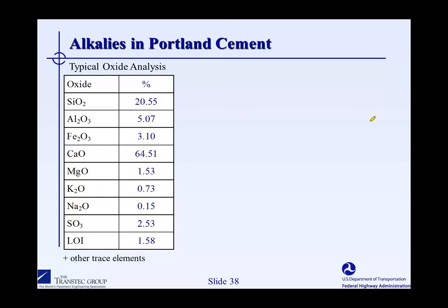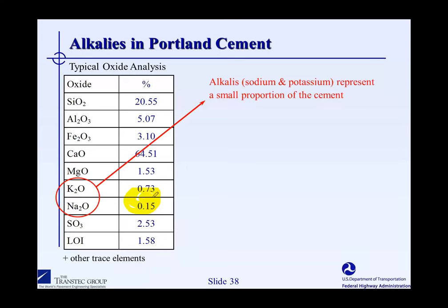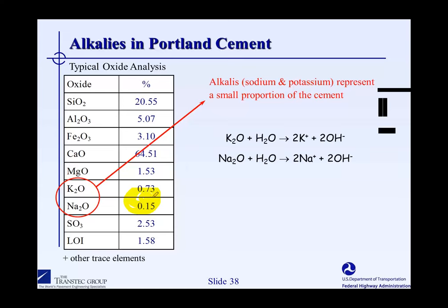If we look at a typical oxide analysis, which you can see here on the left, we know Portland cement's a calcareous material, it's predominantly calcium oxide. Most cement plants are sited near a source of limestone. That's the main ingredient. And then the second highest ingredient is silica, and then we have lesser amounts of alumina and iron. And generally, those four compounds will make up somewhere in the region of 90% or more of the composition of the Portland cement. The alkalis, the potassium oxide here and the sodium oxide here, actually represent a very small proportion of the cement. But they're important because once we mix the cement with water, it's the alkalis that are the main soluble phase, and these alkalis actually pass directly into solution.